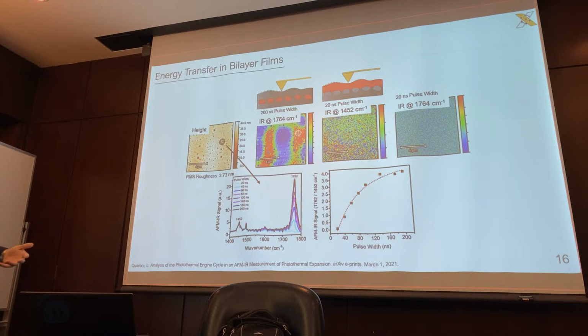So this is what we actually saw. And we could see this pattern up to over 100 nanometers in depth in terms of a barrier layer, which is pretty surprising. So this is kind of the setup that we had in the top hand portion. The red areas are our target material. You see it's blended with our barrier material. And this is our height here. We don't really see much of any features other than these little pits or dots. Focusing the laser on 1764, which is targeting our PLA, which is blended here in the red zone, we can clearly see them appearing here.